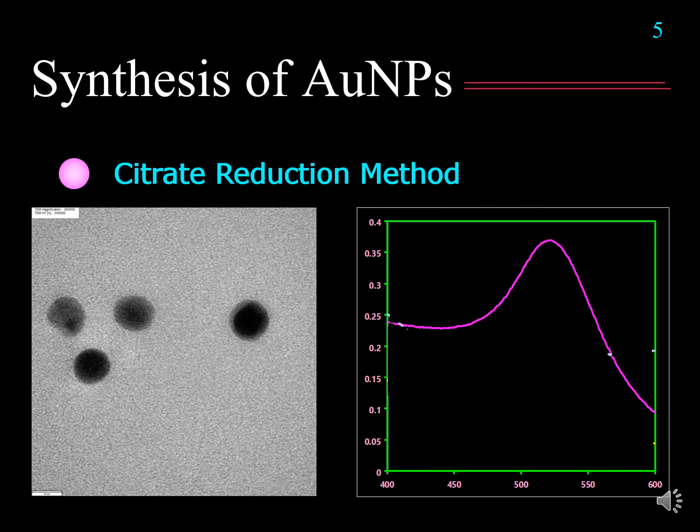So as you can see here, the absorption band from UV-visible spectroscopy, we can see the absorption maximum at about 500 something, and this is due to the surface plasmon resonance. So as I said, the light with the wavelength about 520, this electric field can resonate with the electron clouds on gold nanoparticles with this shape and size.